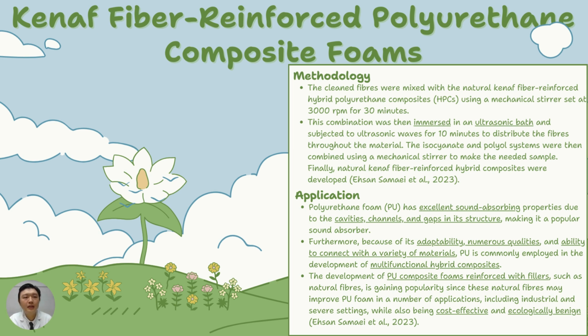So this is the last one, where we talk about the kenaf fiber reinforced polyurethane composite foams. So how do we produce it? We first clean the fiber and then mix it with the polyurethane using a magnetic stirrer. This combination was then immersed in an ultrasonic bath and subjected to ultrasonic waves for 10 minutes to distribute the fiber. The isocyanate and polyol system were then combined using a mechanical stirrer to make the needed sample. Finally, the natural kenaf fiber reinforced composite was developed.